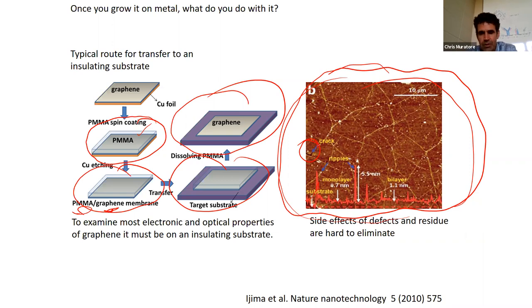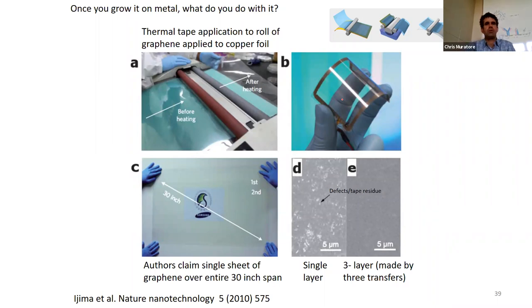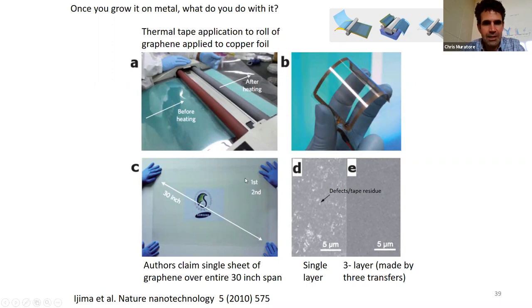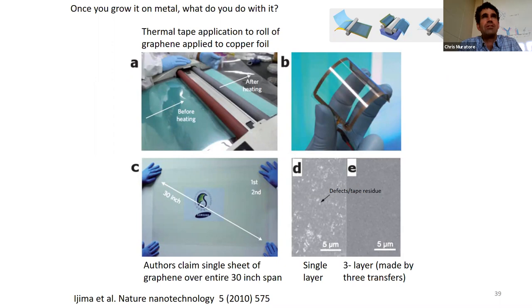There are other transfer methods. You can use thermal tape — sticky at one temperature and not sticky at another. You stick it to the graphene on copper, peel it off, stick the graphene-tape combination on your target substrate, heat it with a heat gun, and the tape falls off while the graphene adheres. This technique can be scaled up to large areas. The quality won't have that ultra-high mobility — a factor of 10 higher than silicon — but it still demonstrates useful properties, and without trying these large-area transfer techniques we may never realize some benefits of 2D materials.